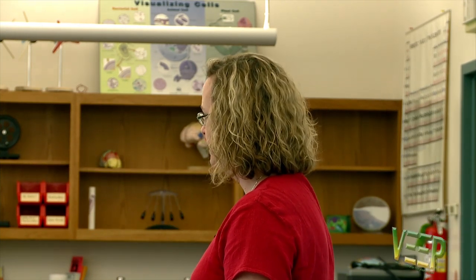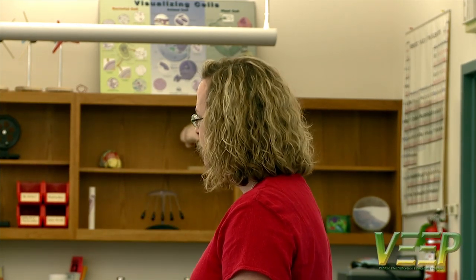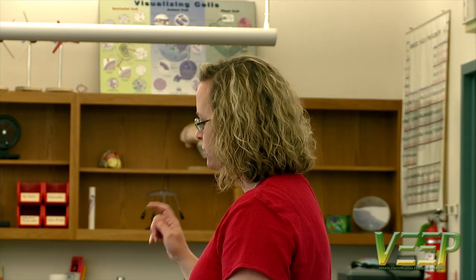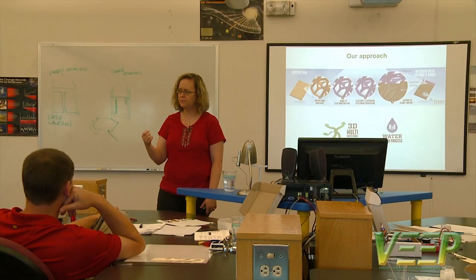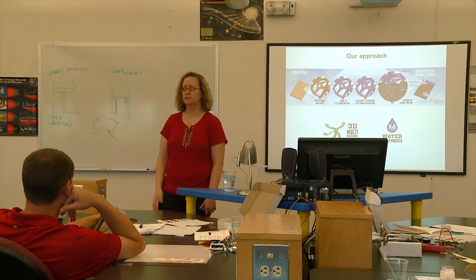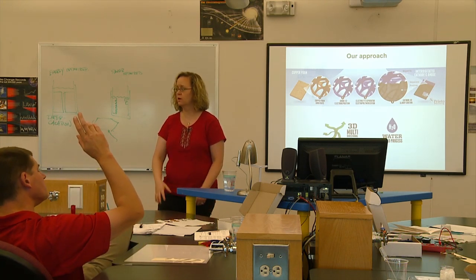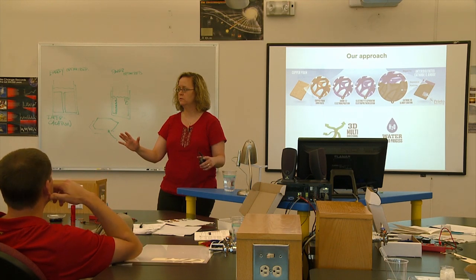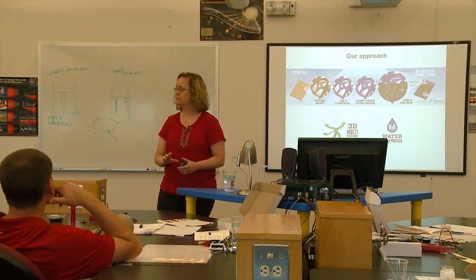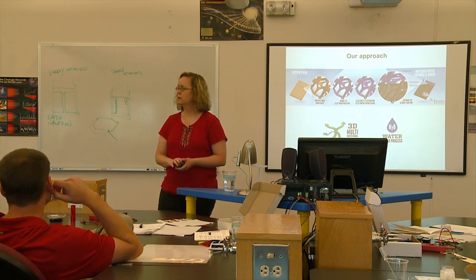We take it out, put it in another rinse tank, put it in a polymer tank. That one I'll show you, that's a little trickier. We coat it, then we do a quick test to make sure it's perfect. If it's not perfect, we do a second coating. Then it goes in another rinse tank, and then it gets dried. So you can recycle your material, you don't have to reject it. That's right. In semiconductor, you get one shot. That's right.